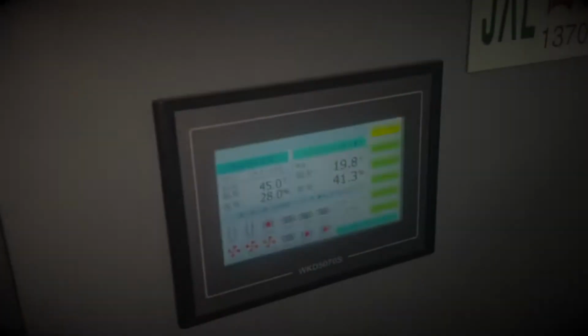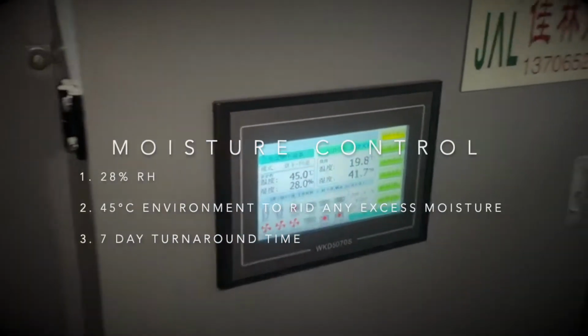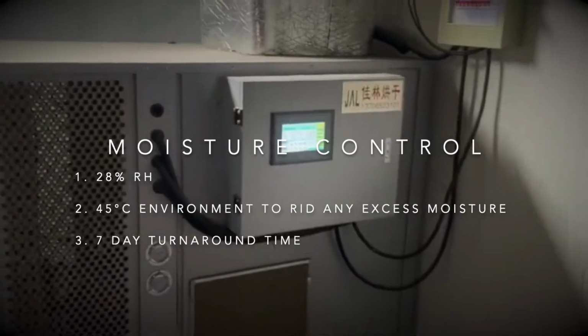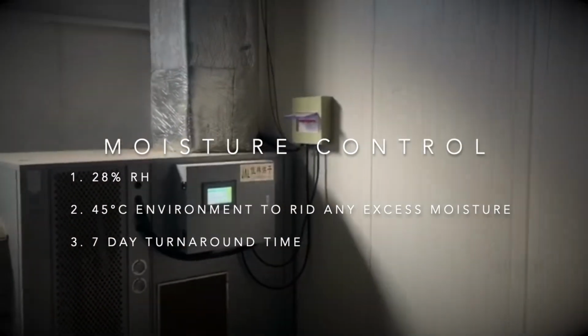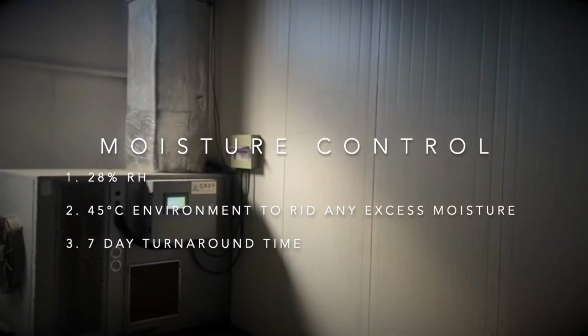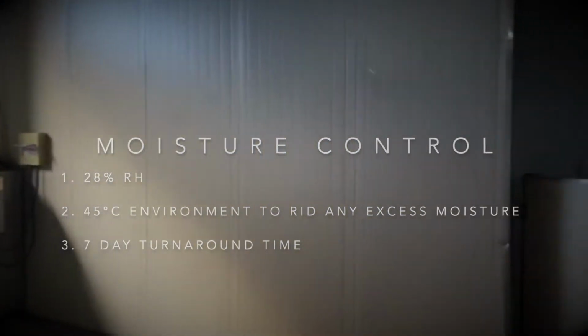Phase 4, moisture control. We need to maintain 28% relative humidity and 45 degrees Celsius to ensure the removal of all excess moisture. This process usually takes around 7 days.